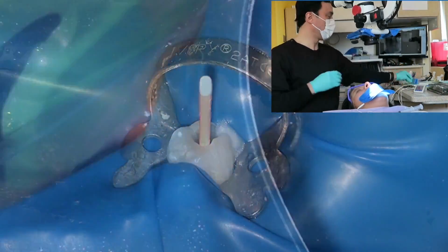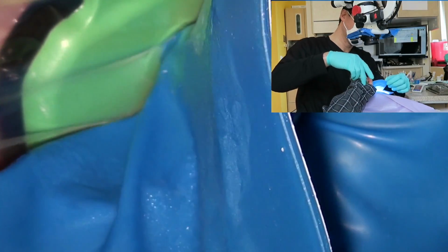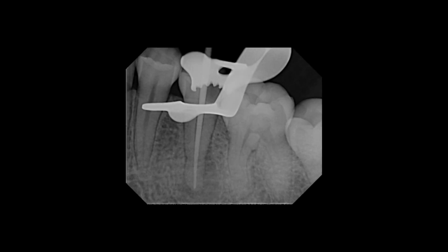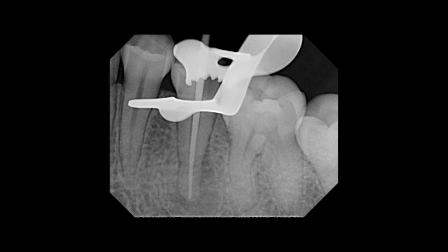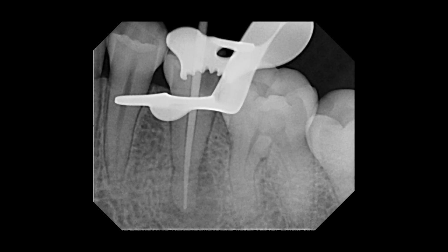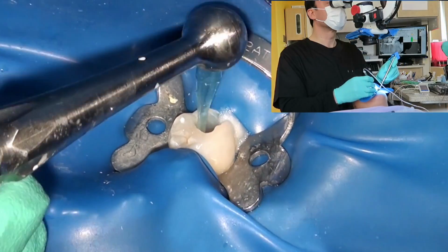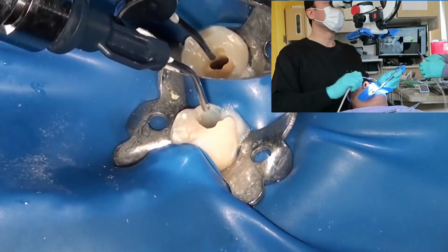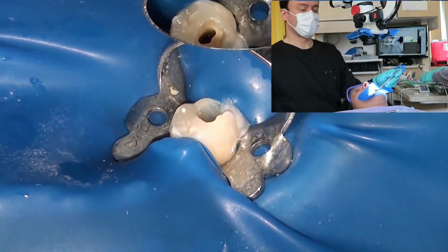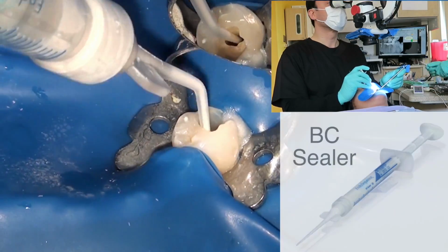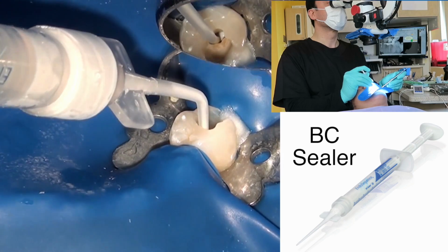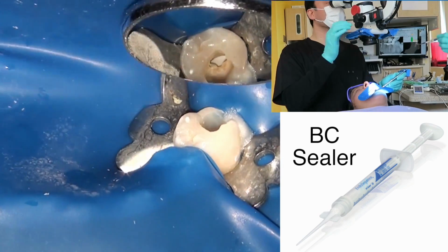Now I'm fitting the matching endosequence BC cone with my final preparation size, and take a check radiograph to show whether we are seating the cone all the way to the end, which confirms that. Now all you need to do is really just to dry with your negative pressure. You don't need to do a lot of heavy dehydration, because you're having a hydrophilic sealer.